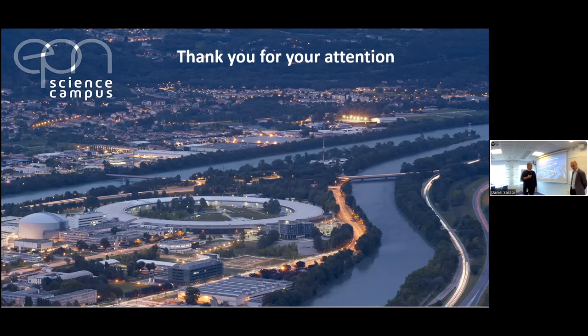I just want to briefly comment on these claims of local symmetry breaking by the PDF techniques. That example you showed. I have to say that I basically disagree with this interpretation because, as in this case, most of these observations are made around second order phase transitions. In the example you showed, you had a tetragonal to cubic phase transition which was continuous. What we know from the Edinburgh School of soft mode physics is that you've got a dynamic instability with associated atomic displacements which will look like the low temperature distorted phase. And with the PDF method, you're, of course, measuring the instantaneous atomic correlations, not the time average ones that you see with diffraction. And that's why it looks like you have this local symmetry breaking.